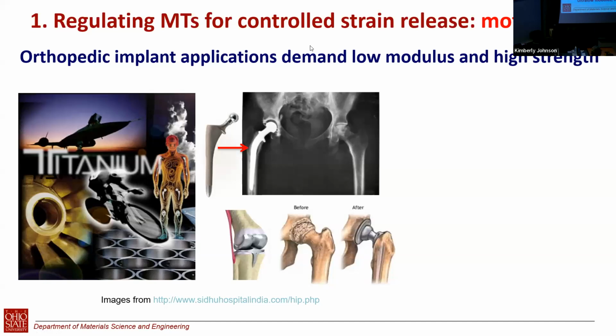Then when you lower the temperature or apply a little bit higher stress, you can have this layer transform. And then this layer is again confined by the next layer, and so on and so forth. So in this case, the transformation is going to go from this one to this one. You transform a little bit at a time while you increase the stress a little bit at a time. So that's the hypothesis, and we can design those microstructures.